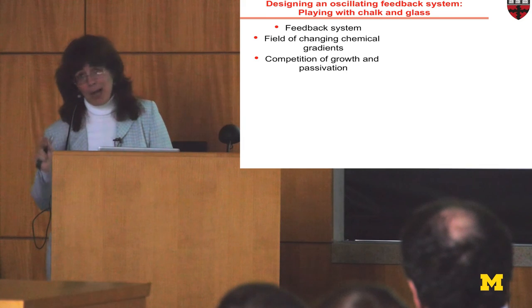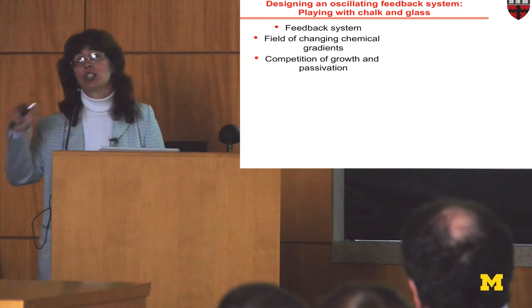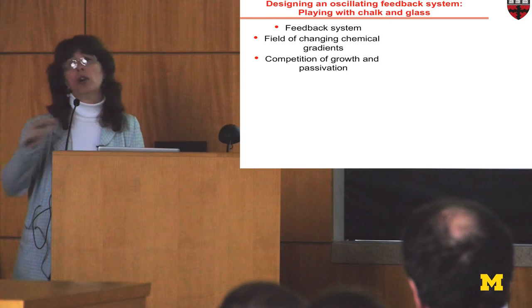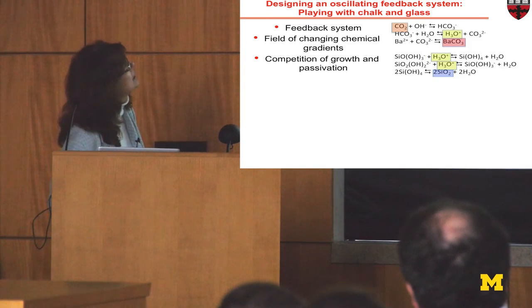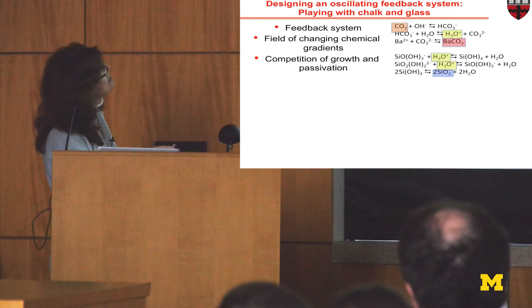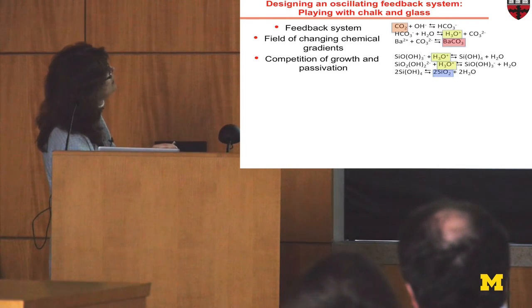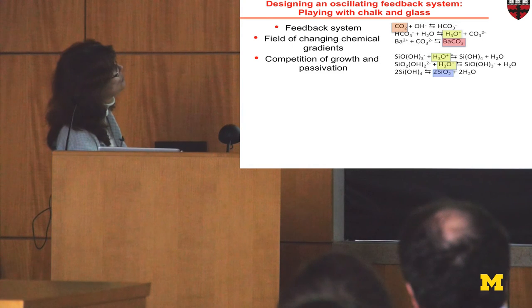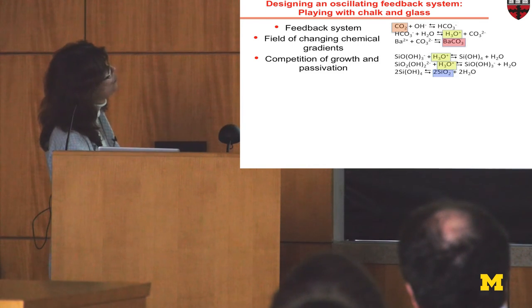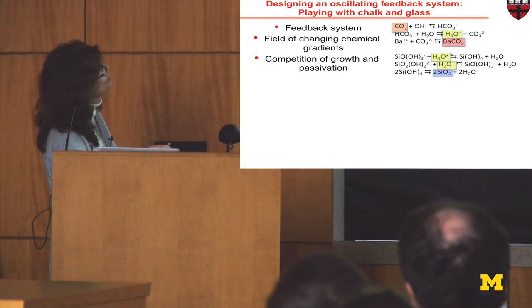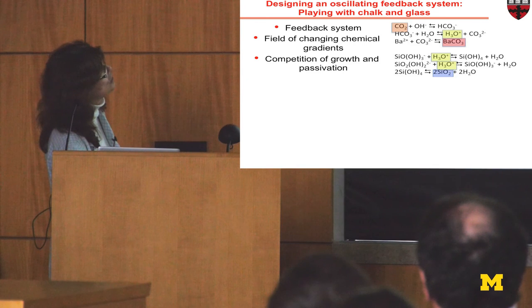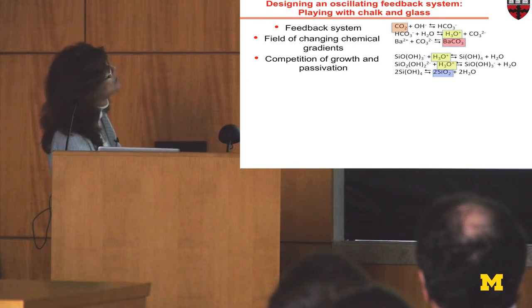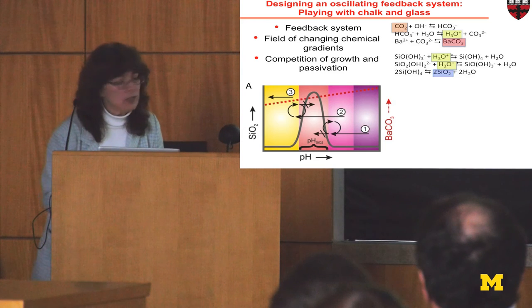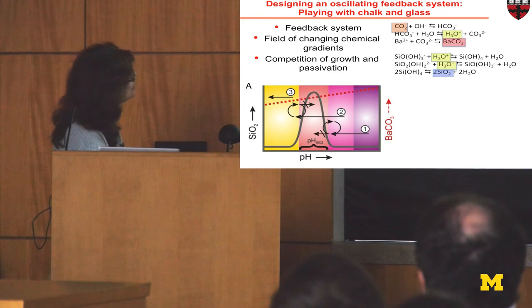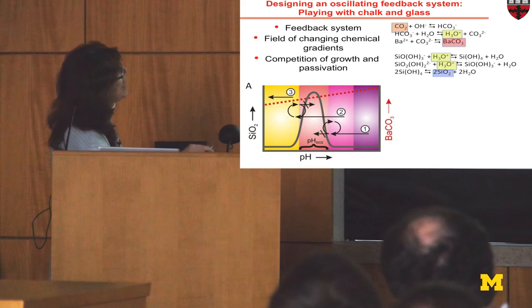It's bioinspired, but without cells or biology in any way or form, and even without polymers in this system. But one can think about a system where, when chalk is forming, it creates conditions for glass to form. Now glass begins to form and changes the microenvironment in such a way that it blocks the formation of chalk. At a certain moment, pH changes again, and the system circulates between these two phases, and we create an interesting feedback system. Here's where pH, where glass can form.